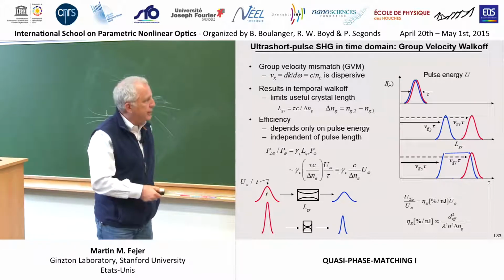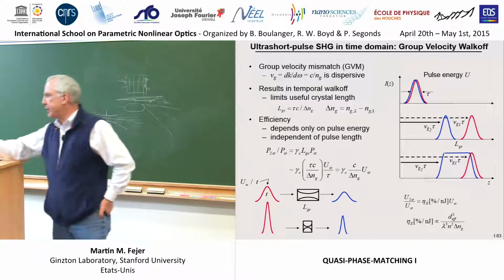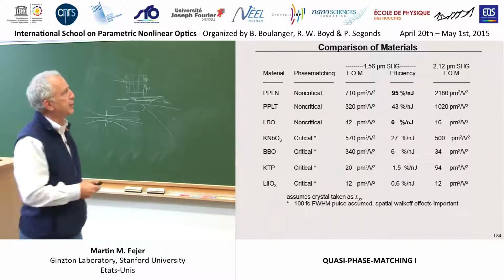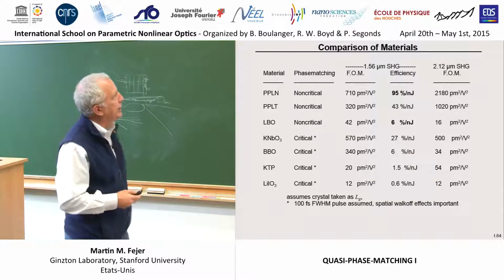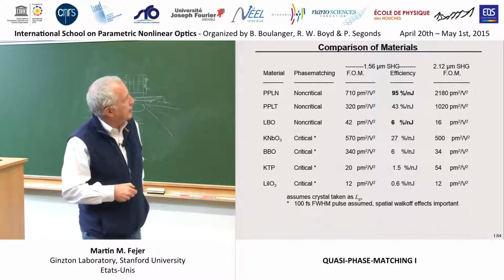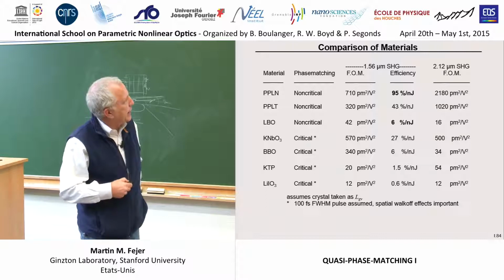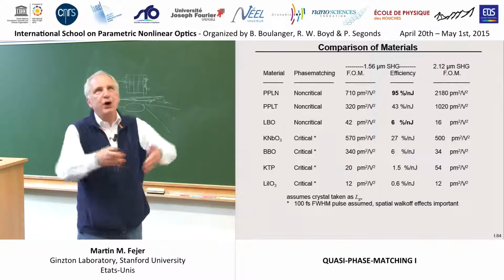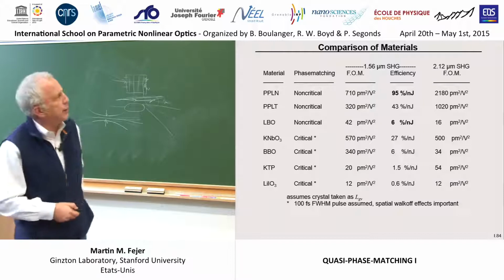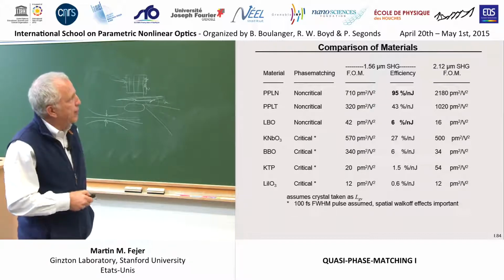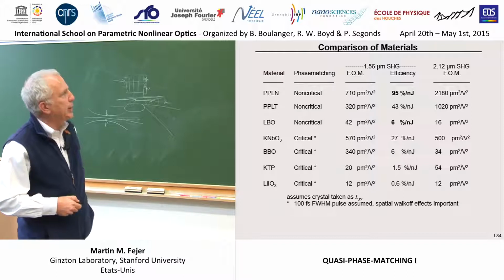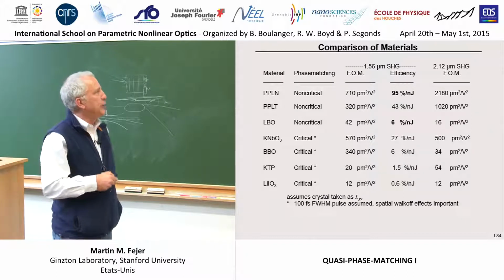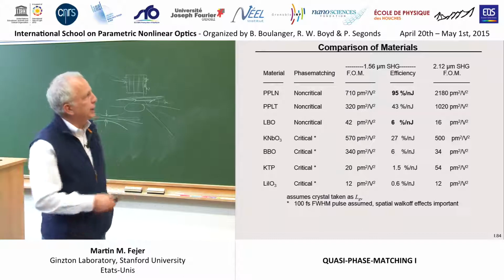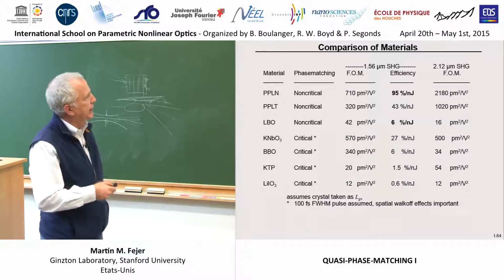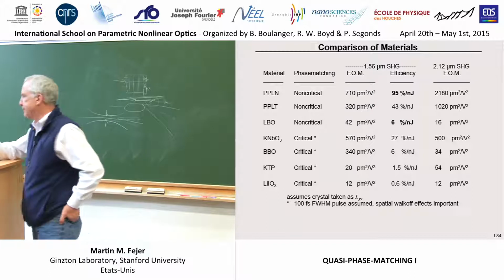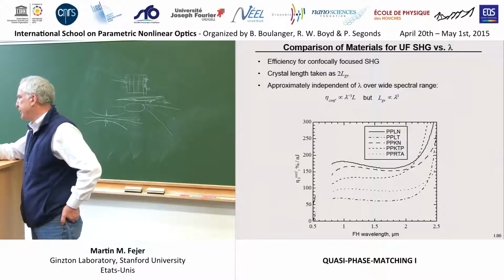But it also turns out they have such a large nonlinear coefficient that when you're all done, if you look at the figure of merit, for example, for doubling 1.5 micron radiation, lithium niobate and lithium tantalate are actually in the range of 100% per nanojoule. You can do efficient interactions with picojoule pulses, and that's much better than LBO or potassium niobate or BBO, which have less group velocity mismatch, but they have far less nonlinearity. So when you're all done, you end up doing better in the quasi-phase matched media. We don't have to go into that.